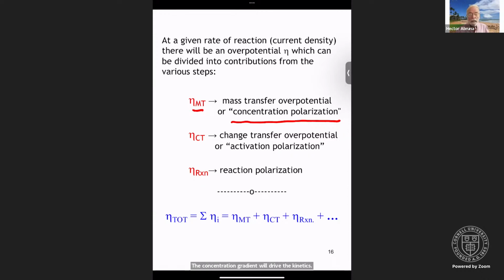And so if, let's say, you have an electrode surface, you're consuming material close to the electrode surface. Because you're consuming it, the concentration will drop. That creates a gradient. That gradient is responsible for further mass transport. The higher the concentration you have, the higher currents you can sustain before you polarize, because you're basically at a rate that is limited by how much stuff you can bring to the surface.